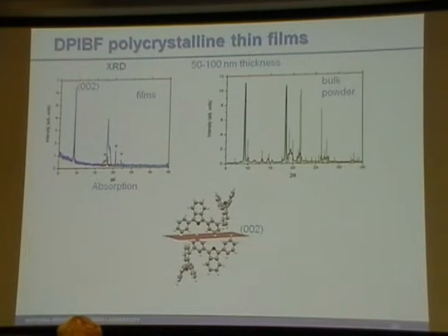It's not that easy to do spectroscopic experiments on single crystals of organic molecules, because often they're hard to control the thickness, and if they're very thick or full of defects, often the experiment is difficult. So what we do is we deposit polycrystalline thin films using what's called thermal evaporation. We put powder of the compound in a boat, and we heat it up under vacuum. It vaporizes and deposits in a nice, thin, and uniform way on different substrates. So this is how we make films to study by spectroscopy.